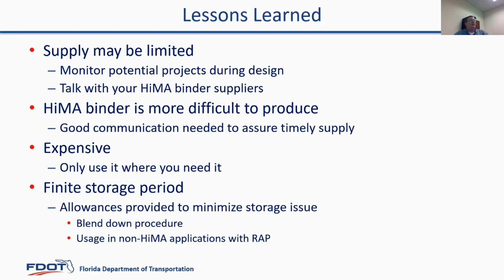You don't want to get in a situation where you can't get the binder to your projects and you cause delays. It is going to be more difficult to produce, especially early on, as the suppliers learn to produce it. They've gotten a lot better and a lot more used to it in Florida, but it does take them longer to make it. Some of them also say it'll take more storage capacity at the yard too. So it's important to have good communication between your contractor, your asphalt producer, and your binder supplier. This isn't the thing where they call Friday and expect to have the binder shipped on Monday. We found that 2 to 3 weeks, especially early on, is the lead-in time you want to give them.